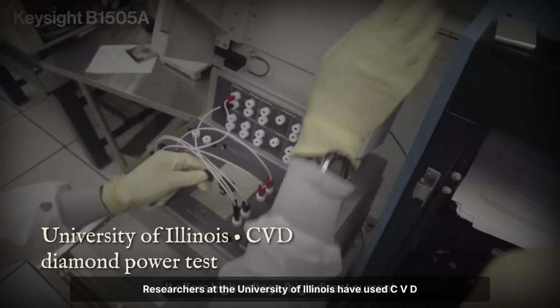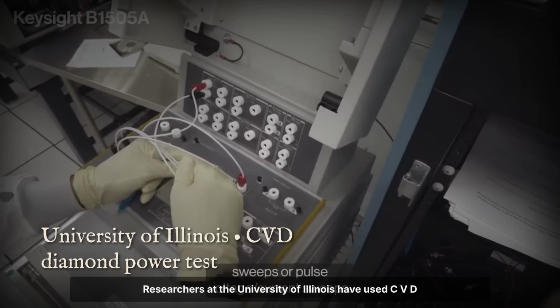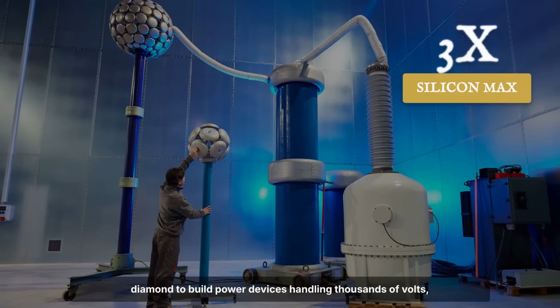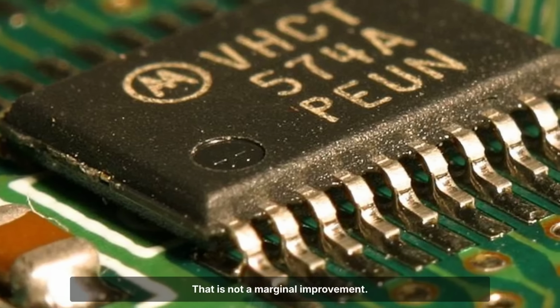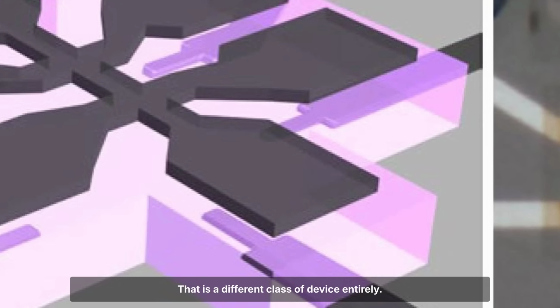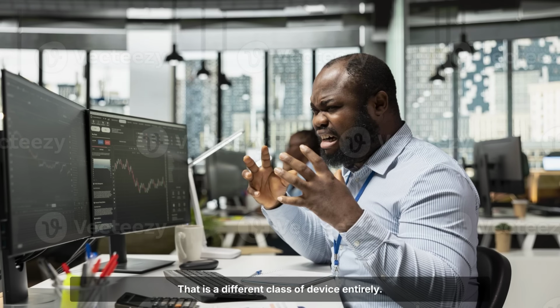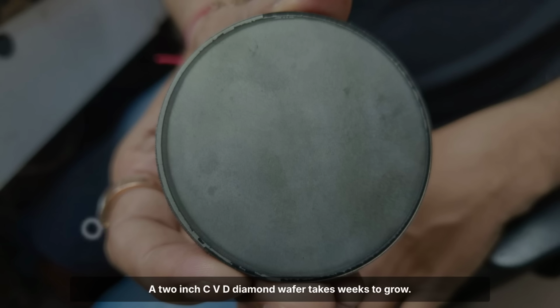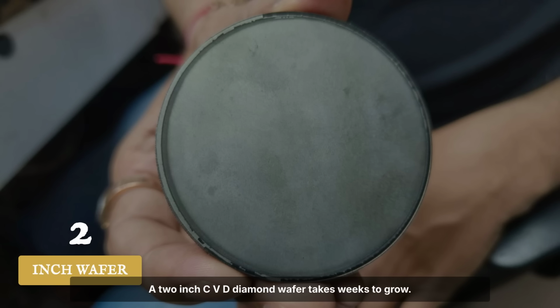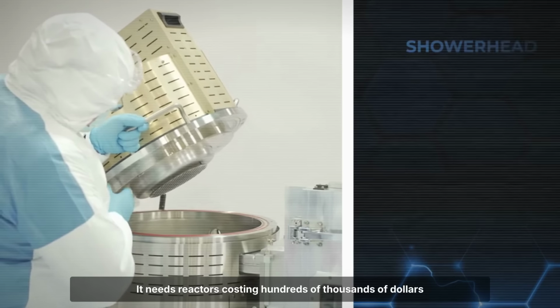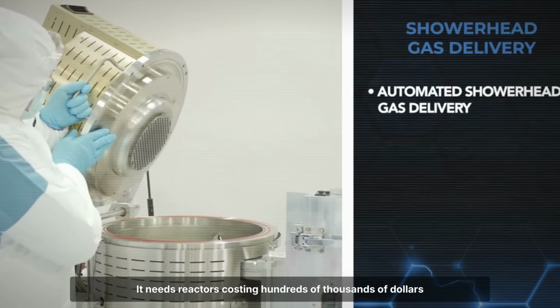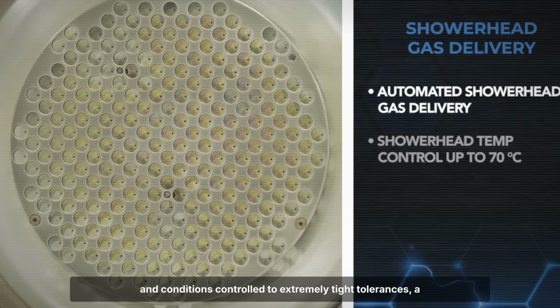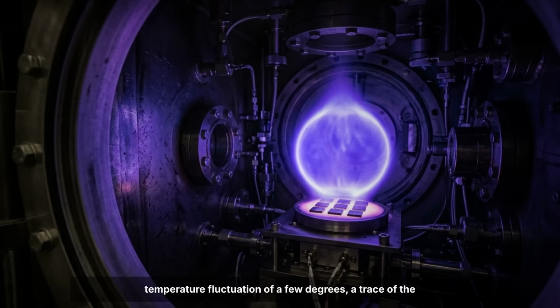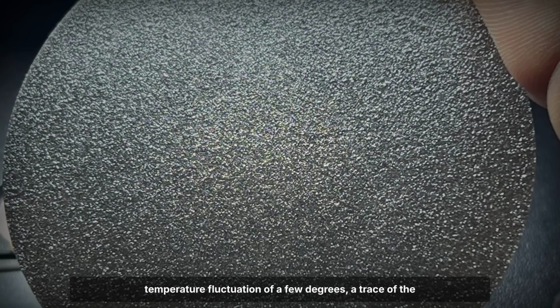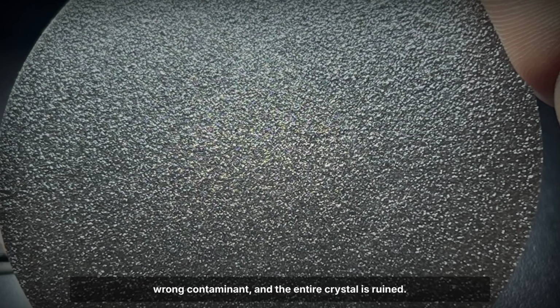Researchers at the University of Illinois have used CVD diamond to build power devices handling thousands of volts, several times the maximum silicon can manage. That is not a marginal improvement, that is a different class of device entirely. But the economics are brutal. A 2-inch CVD diamond wafer takes weeks to grow. It needs reactors costing hundreds of thousands of dollars, and conditions controlled to extremely tight tolerances. A temperature fluctuation of a few degrees, a trace of the wrong contaminant, and the entire crystal is ruined.